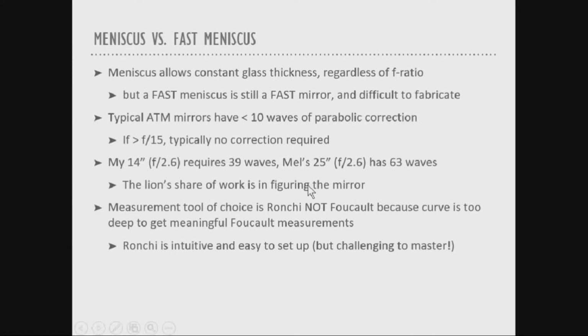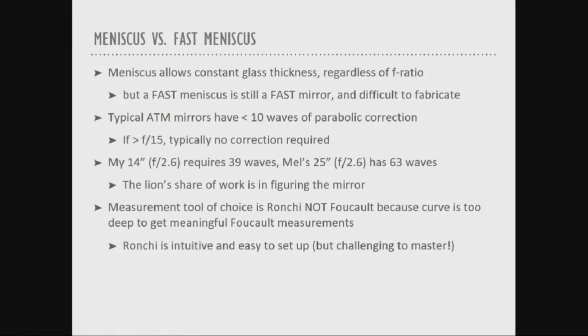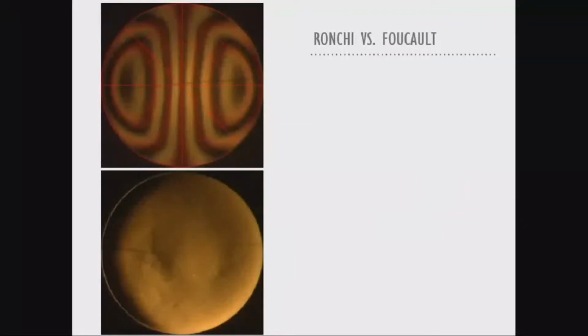It is difficult. The measurement tool of choice for this type of thing turns out to be the Ronchi test and not the Foucault test. Typically, ATMers use Foucault tests. Sorry, when I say typically, I mean up until relatively recently, when there are actually a number of really good alternative tests. But historically, the Foucault test was the ATM tool of choice. But the Ronchi test is a much more appropriate test to use for this, because the curves are so steep, it's really difficult to get accurate Foucault measurements. And the Ronchi is a very intuitive and easy test to set up.